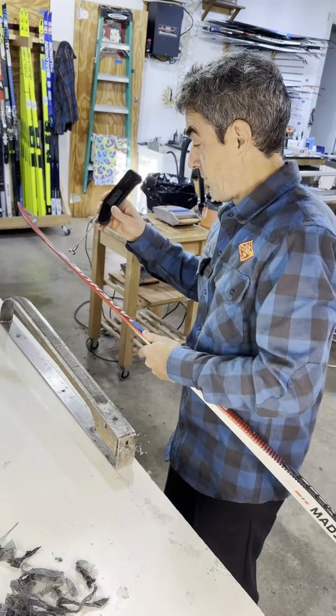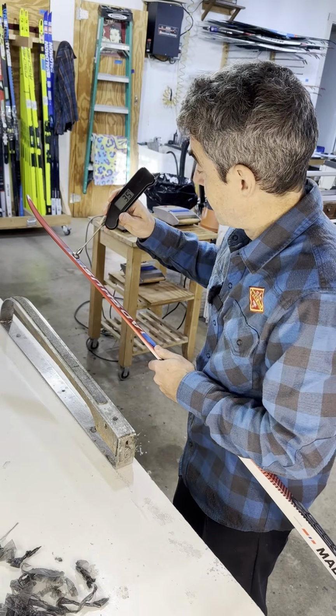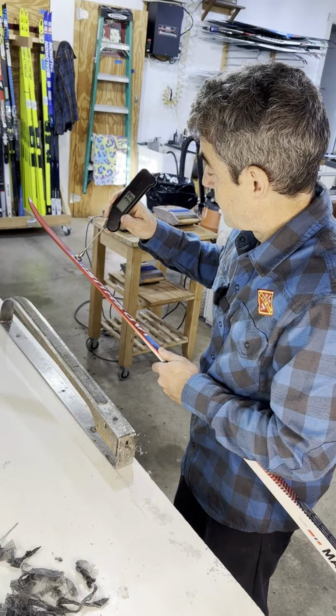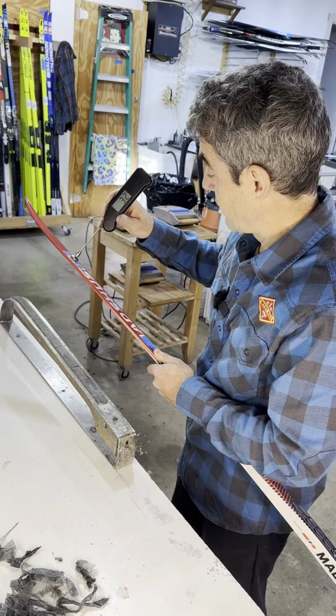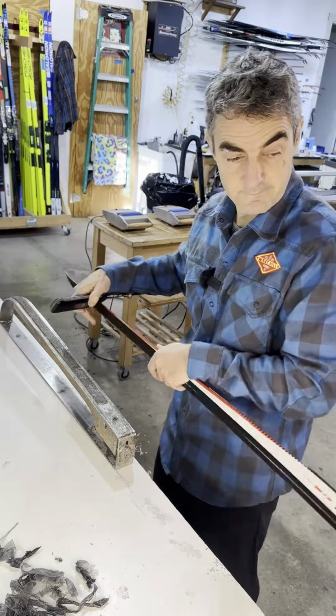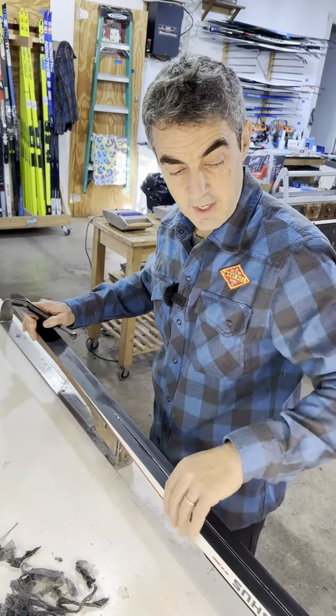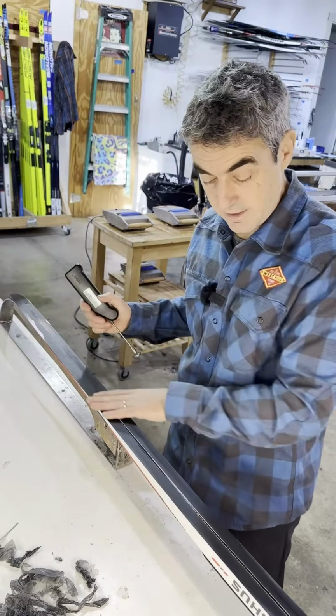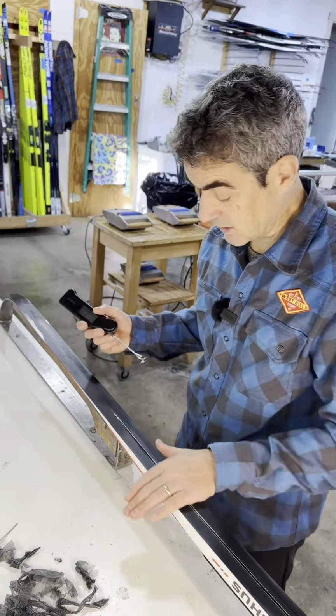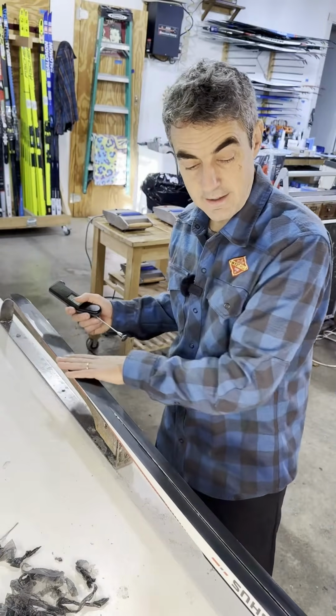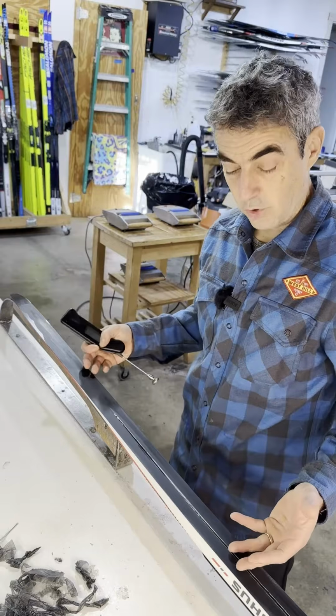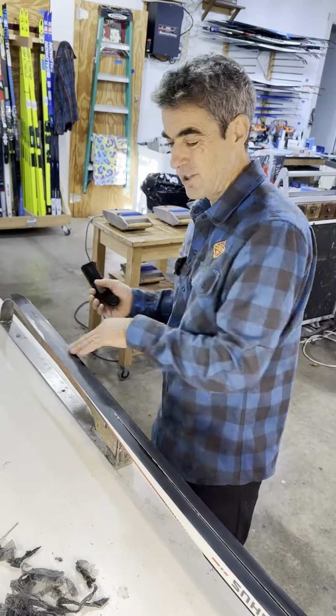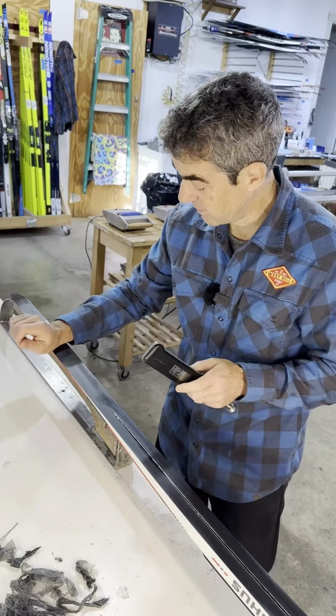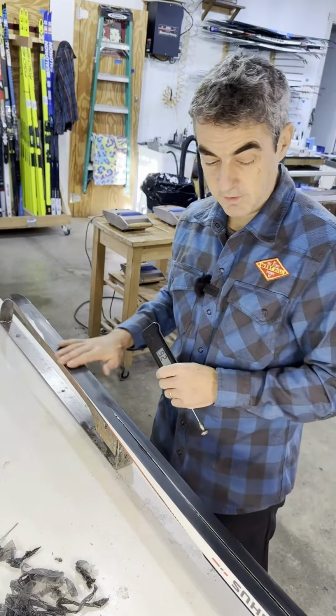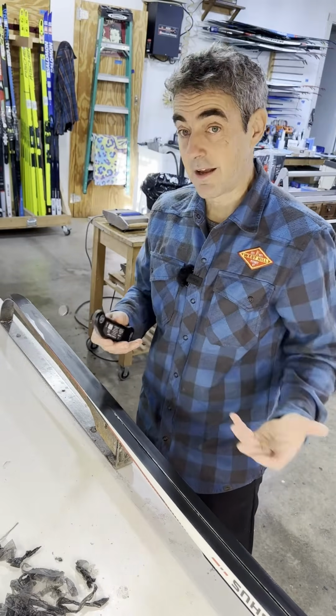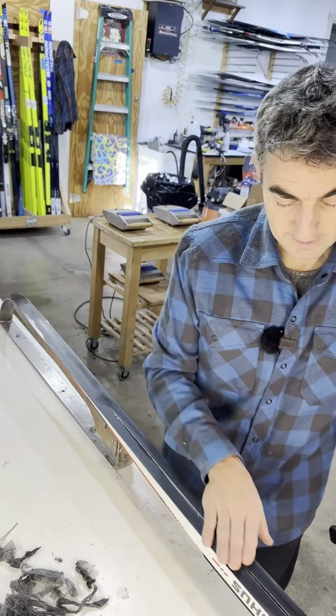What's the temperature on the top side of the ski? So we've already got heat propagating through the ski. We're 32 degrees on the top sheet. Still very safe. We really, really haven't overheated the structure of the ski that much. But before we put the iron back on, we do want to let this whole thing cool back down close to room temperature. I kind of use that baby bottle test like this. Oh, that's a little too hot for the baby. That means I'm not putting the iron back on. So in the meantime, I can take my other ski down and work on that one.